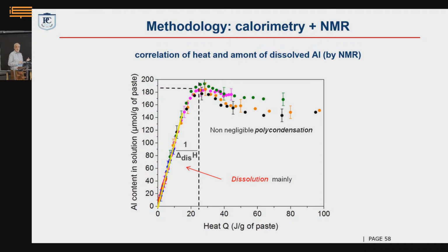We can plot one versus the other. So we evacuate the time variable, so we evacuate the kinetics in a sense, okay? And we just have how much heat is released per aluminum dissolved in solution. So we have the heat of dissolution, and you see that all my curves that were measured at different metakaolinite concentration actually collapse onto a master curve, because yes, the kinetics was not the same because the surface area was not the same, but the mechanism, the chemistry is the same, so they collapse on the same curve at the beginning. There it's a little more complicated, but they collapse on the same curve here.